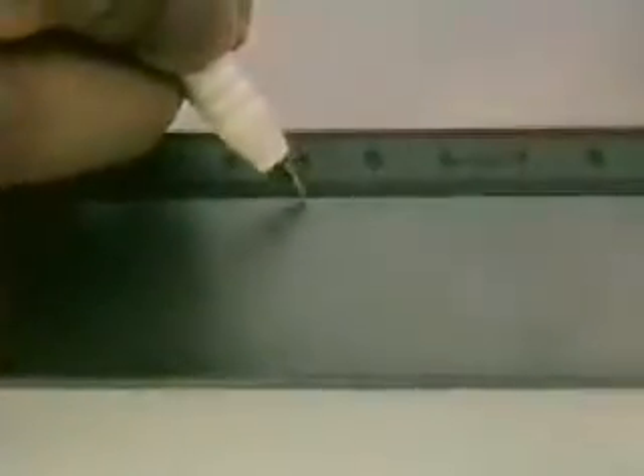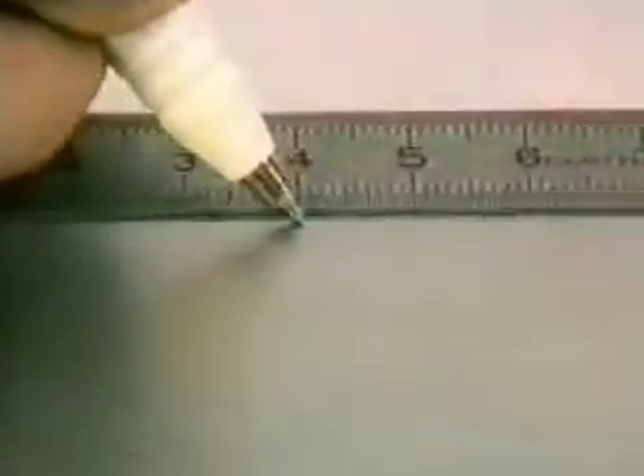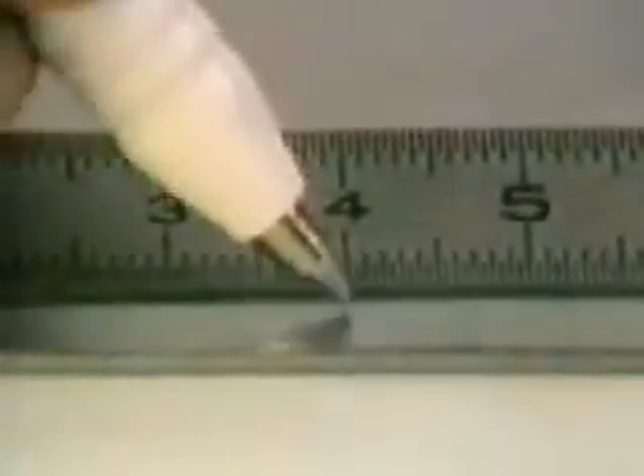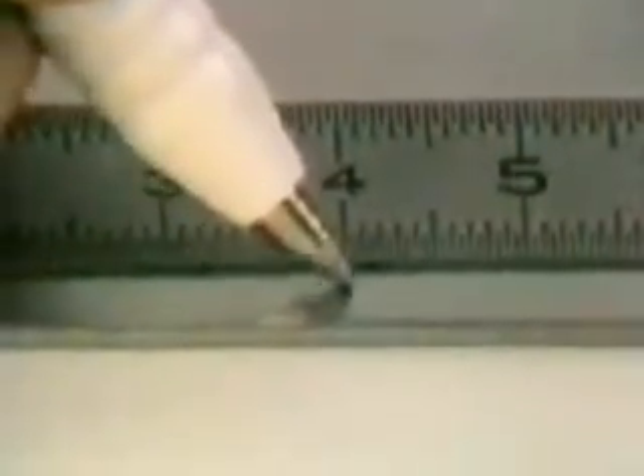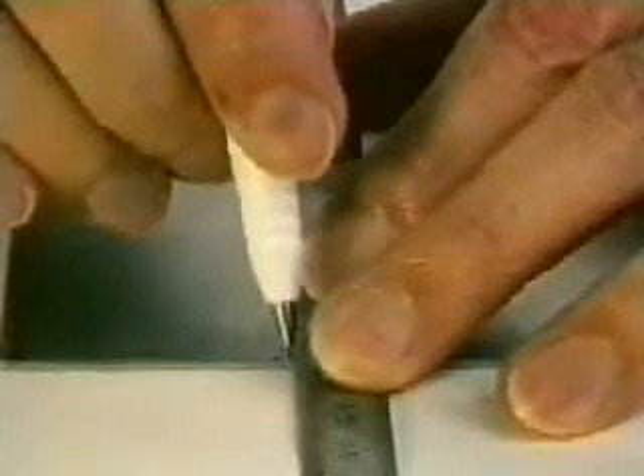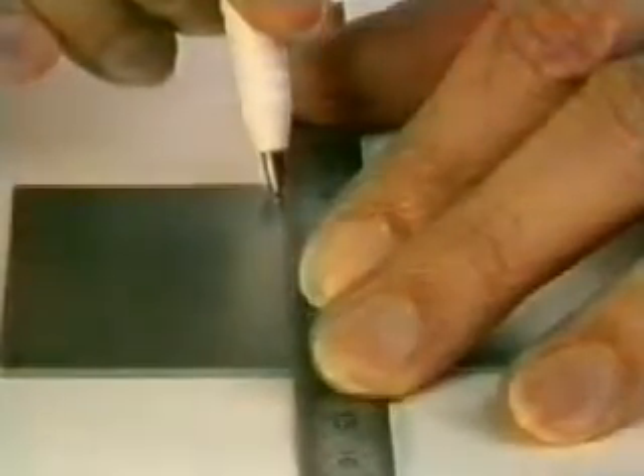In the third stage, a cross is made at the point stated in the mounting plan. A scribe is not used for this task, since it would only cause marks in the surface and could damage the test object. A ballpoint pen in which the ink has run out produces clearly visible lines under moderate pressure, but without leaving harsh channels. If the pen still contains ink, then the ink must be completely washed off the test object using solvent, because otherwise the bonding will be impaired.